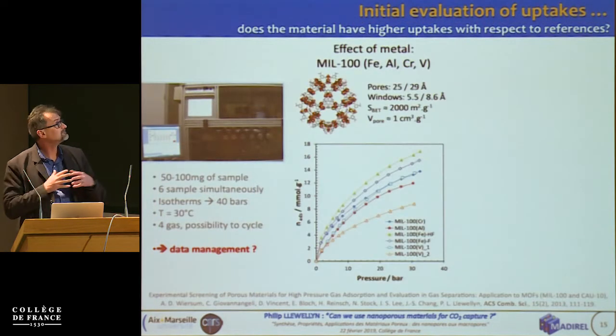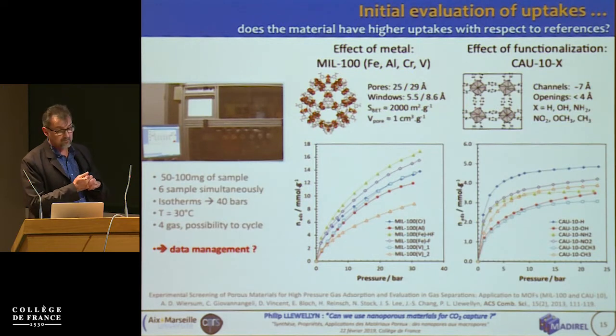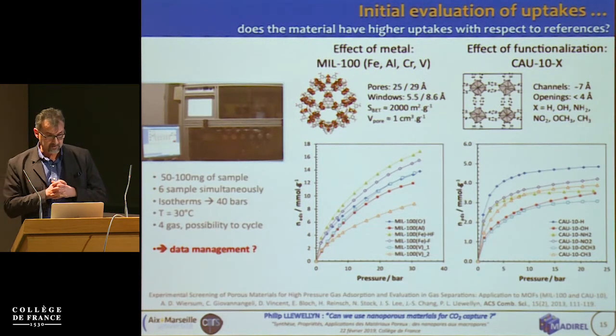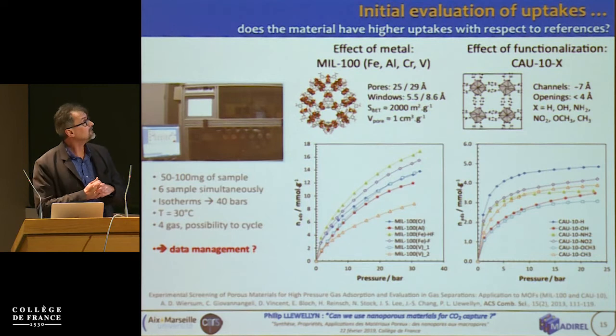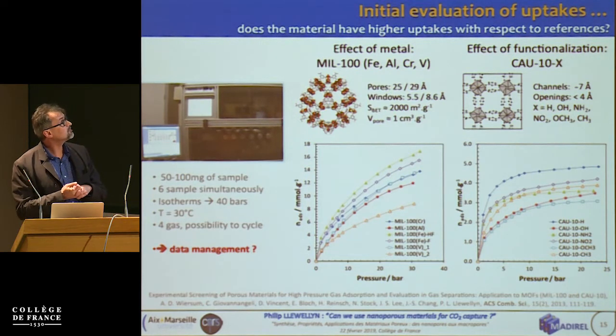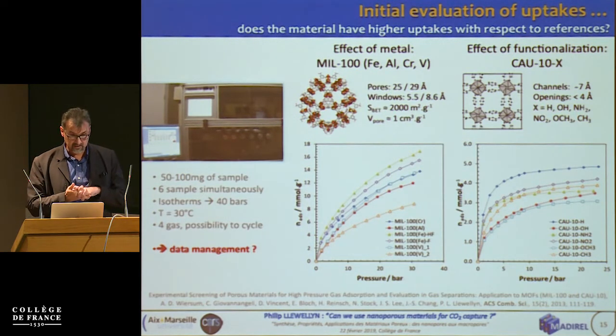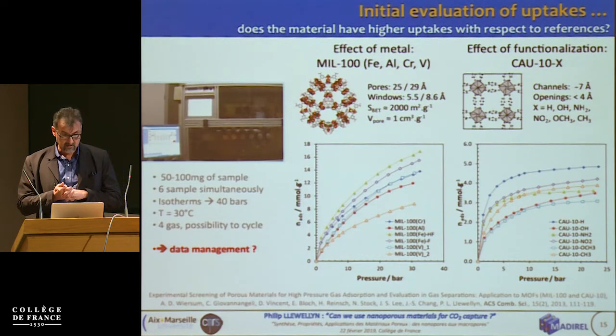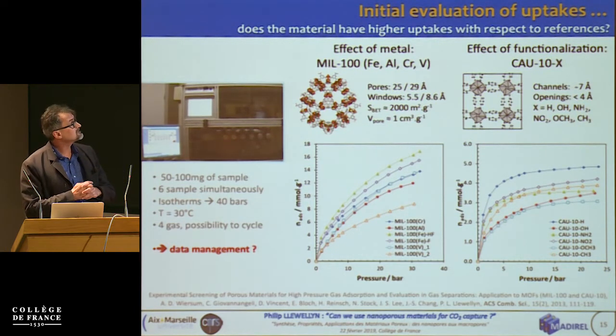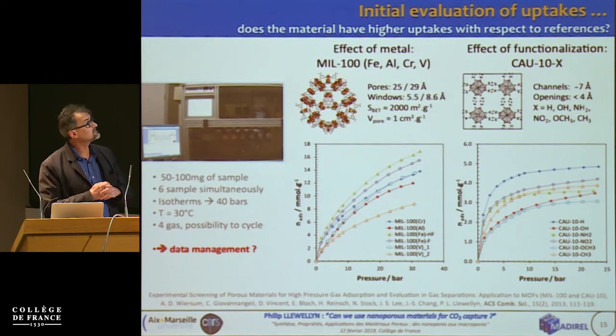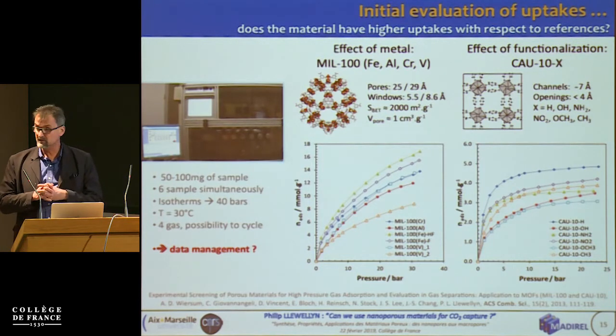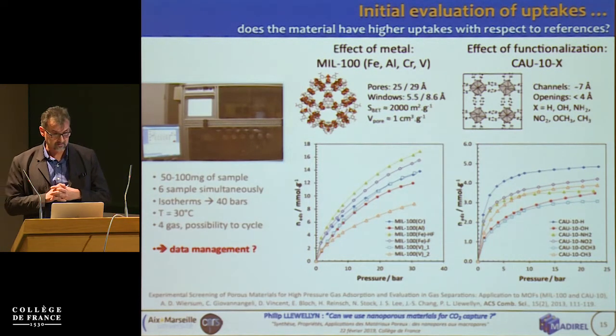Okay, so what we do in the lab. So in the lab, we've built our own bits of apparatus to work at room temperature. We have 2 pieces of apparatus which can work each with 6 samples each, so we can work at 12 samples at a time. What we designed is a system in which we can use less than 100 milligrams a sample to get a pretty good idea of what the isotherm looks like, and that's pretty good.